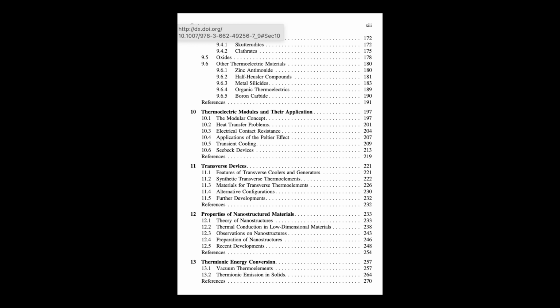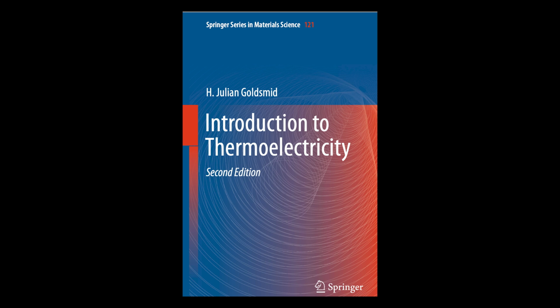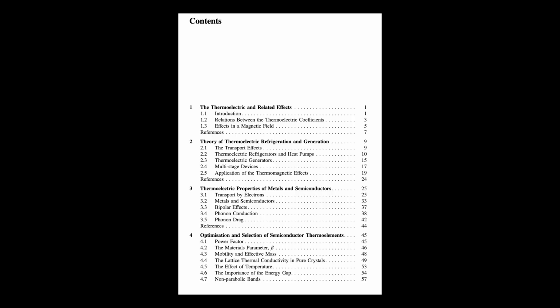Makes sense. Bi2Te3 is also the basis for solid solutions. We talked about the general idea. Why are they so key for Bi2Te3? Right. Solid solutions are great for lowering lattice thermal conductivity. And Bi2Te3 readily forms them with similar compounds. Bi2Te3 mixed with antimony telluride, Sb2Te3, makes excellent P-type alloys. Bi2Te3 mixed with bismuth selenide, Bi2Se3, makes effective N-type alloys. By carefully tuning the mix ratio, you can optimize performance over specific temperature ranges, often better than pure Bi2Te3.